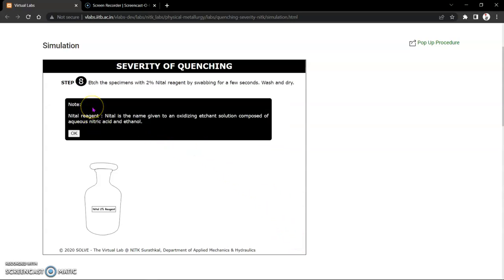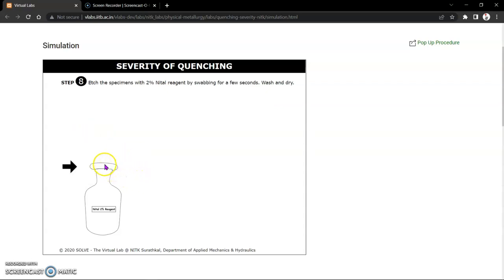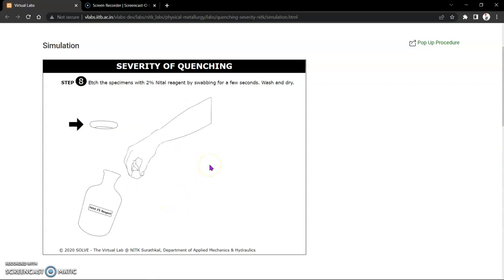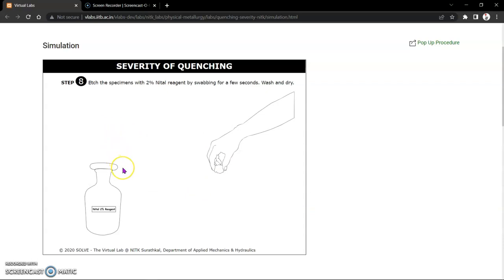Step 8. Etch the specimen with 2% Nital reagent by swabbing for a few seconds. Wash and dry. Note: Nital reagent is the name given to an oxidizing etchant solution composed of aqueous nitric acid and ethanol. First open the Nital reagent and put the Nital reagent on the sample.